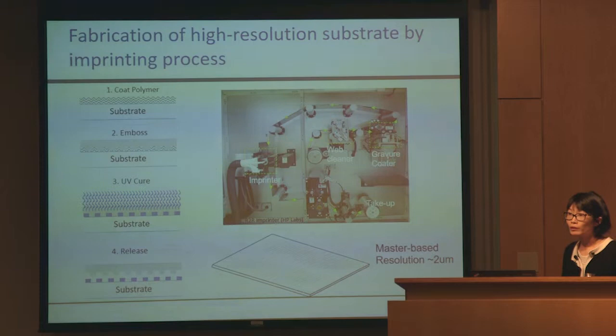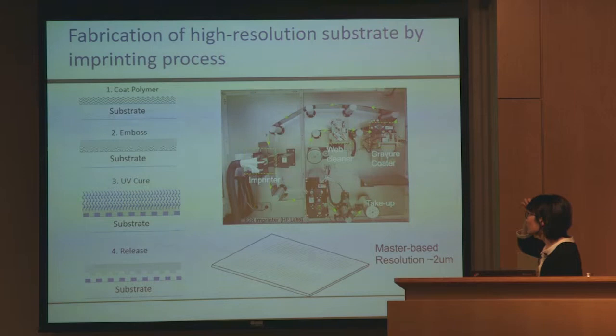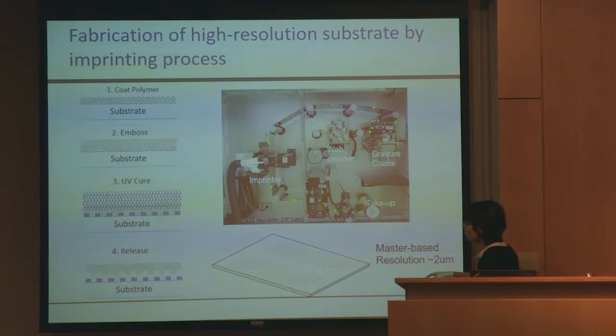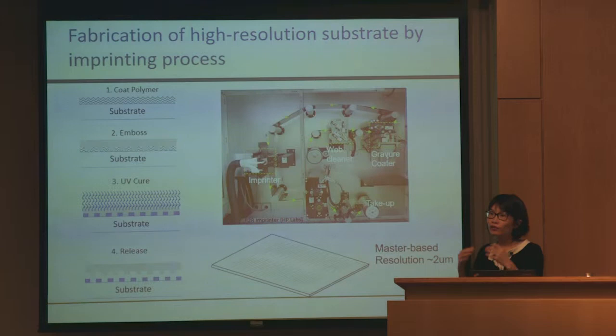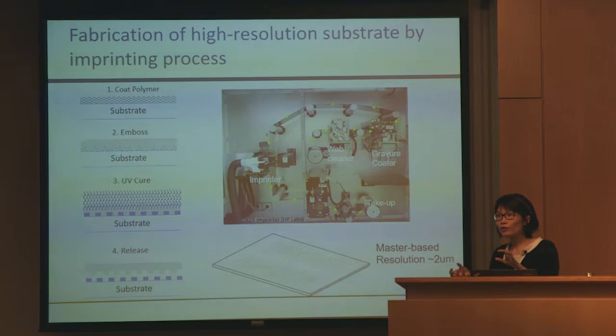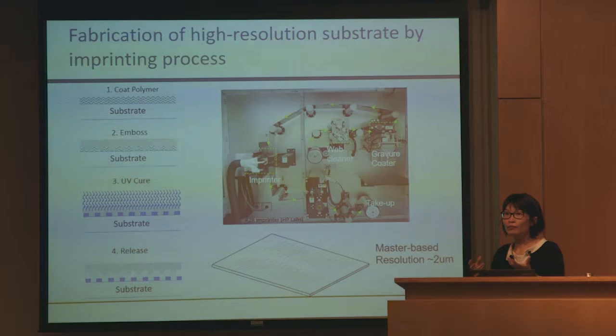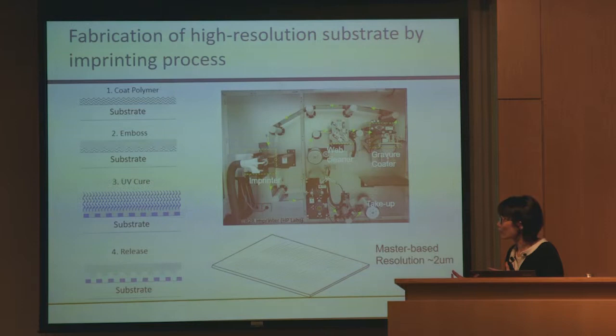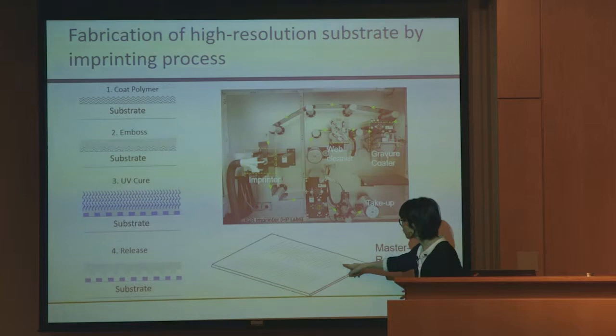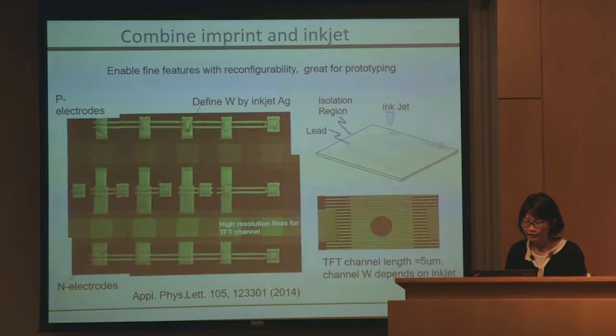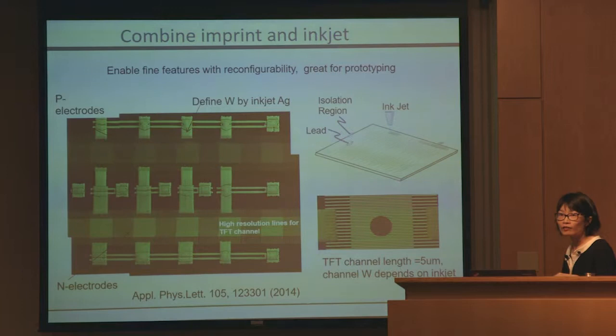And here, this is one of the nano imprinter where we could define a narrow gap between electrodes. The problem with nano imprint is it's good for periodic structures, but then when you have more turning corners, more complex architecture, the fidelity of the pattern doesn't come out anymore. And so for us, building circuit using nano imprint was quite difficult because to adjust the microfluidic of how inks turn corners is very difficult. So to us, we actually combine the periodic nice array we can fabricate with the digital reconfiguration of inkjet.